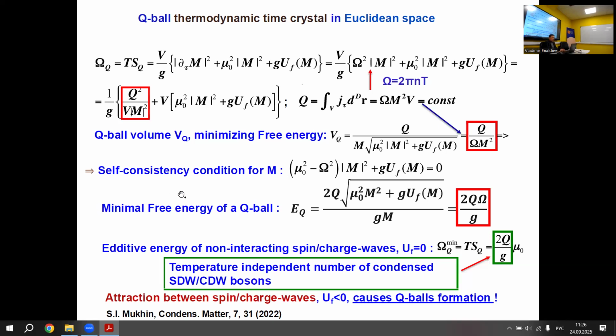And what is also important is that if you substitute this solution back to here, you will find the energy of the Q-ball. And this energy of the Q-ball proves to be proportional linearly to the Matsubara frequency, which means it's linear with temperature, because Q is temperature independent, G is a temperature independent coupling constant. And that's very important because when we further on consider the Boltzmann distribution of Q-balls over their energies, you will see that in the Boltzmann exponent, temperature cancels, because when you write down e to the power minus Eq over kBT, T goes away, and you see it depends on Q over G, and Q over G is actually the number of condensed excitations of spin or phonons condensed in this Q-ball.